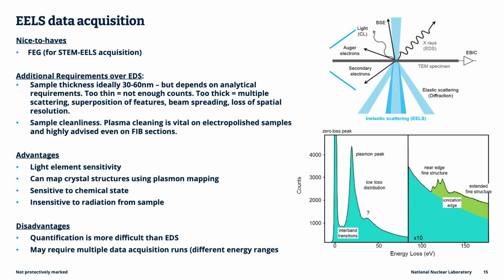It's kind of difficult but possible to model the plasmon shapes for different phases. If you're looking at oxide metal interfaces, it's quite easy because the oxide plasmons are usually very distinctive, as we saw in the example right at the beginning. There are also characteristic ionization edges due to each of the elements. The light element ionization edges unfortunately fall in this low energy region where the signal is really intense and varies very rapidly as well. But it does at least mean that we can potentially map all elements using EELS.